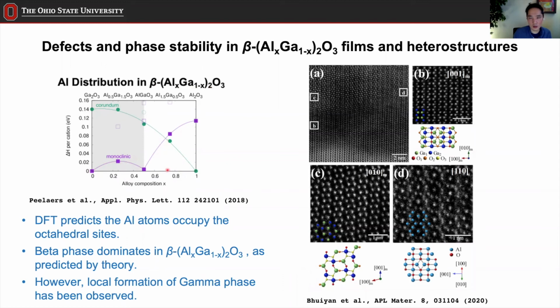That's pretty high. So that's pretty intriguing, right? And also promising, because we want to keep the beta structure, and that's the monoclinic structure, right? And it turns out when the growth happens, that's the case, right? So in most cases, the beta phase is being obtained. I mean, they preserve the original structure. Okay, so this prediction is correct.